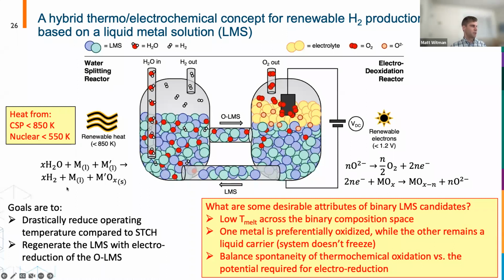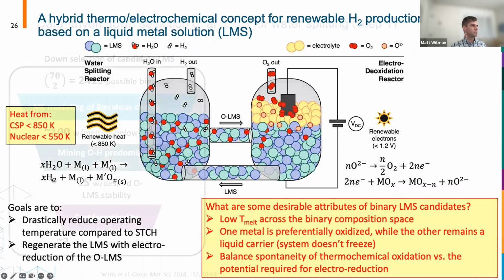So here's the kind of proposed scheme. We have two different metal elements in our melts, and hopefully we preferentially oxidize one of them while the other forms these small, well-distributed metal oxide particles in the melts, while the inert metal remains liquidous as a carrier, and so the system doesn't freeze and we generate hydrogen.